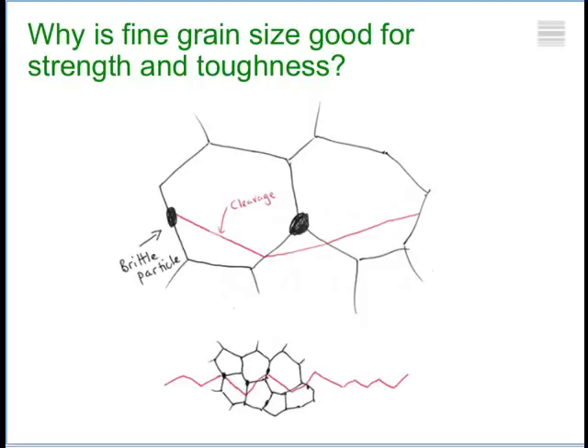So if I go back to this slide, my question to you before the break, based on the fact that we get an increase in strength and toughness by making the crystal size smaller, my question to you was, what is the smallest grain size we could achieve in thermomechanical processing? Because by thermomechanical processing, we can produce very large quantities of steel.